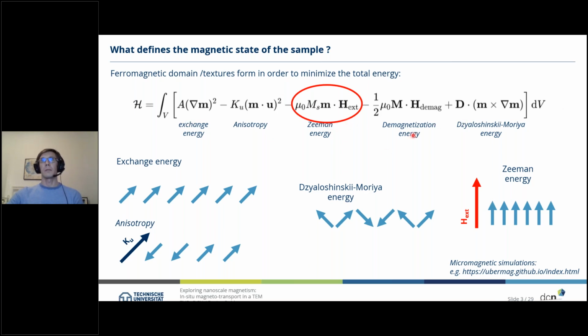All of this has a strong interplay, of course. You can have different constants for the exchange energy, different anisotropy constants, different values of the Dzyaloshinskii-Moriya interaction, and this will then define the material properties and the magnetic properties of your sample. If you want to dig a bit more into playing with magnetic samples and geometries, I highly recommend visiting this website here. It's Ubermag, a micromagnetic simulation software which you can run in the browser. On the one hand it minimizes this Hamiltonian, this energy, but you can also use the outcome to simulate Lorentz TEM images, or magnetic phase images for holography, or anything else.